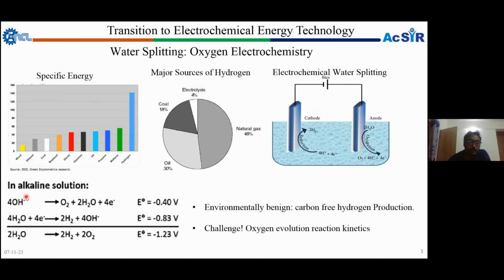The reaction can occur in two ways, acidic condition and alkaline condition. In my work, I am very much interested in the alkaline solution. Here hydroxyl ions form oxygen at a potential of minus 0.40 volt, in a 4-electron process, along with hydrogen formation. The overall reaction, water to hydrogen and oxygen, occurs at a potential of 1.23 volt.